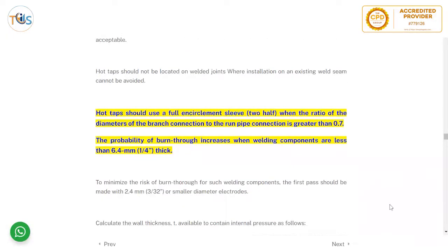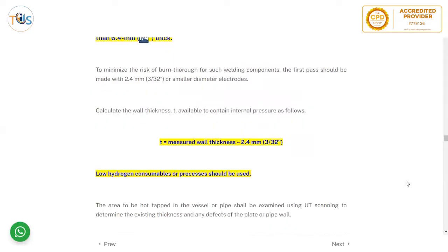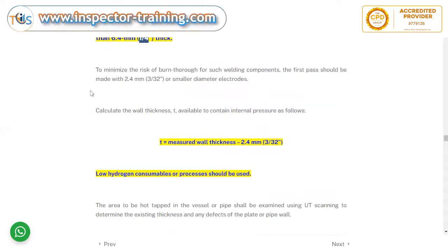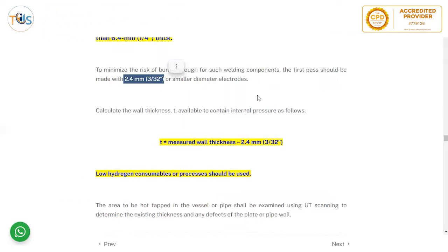Probability of burn through increases when welding components are less than 1/4 inch thick. And to minimize the risk of burn through for such welding components, the first pass should be made with a 2.4 millimeter, this could be an exam question, or a smaller diameter electrode. So use the smallest electrodes, so there is no burn through, because not much heat input or melting of the base metal during the welding.